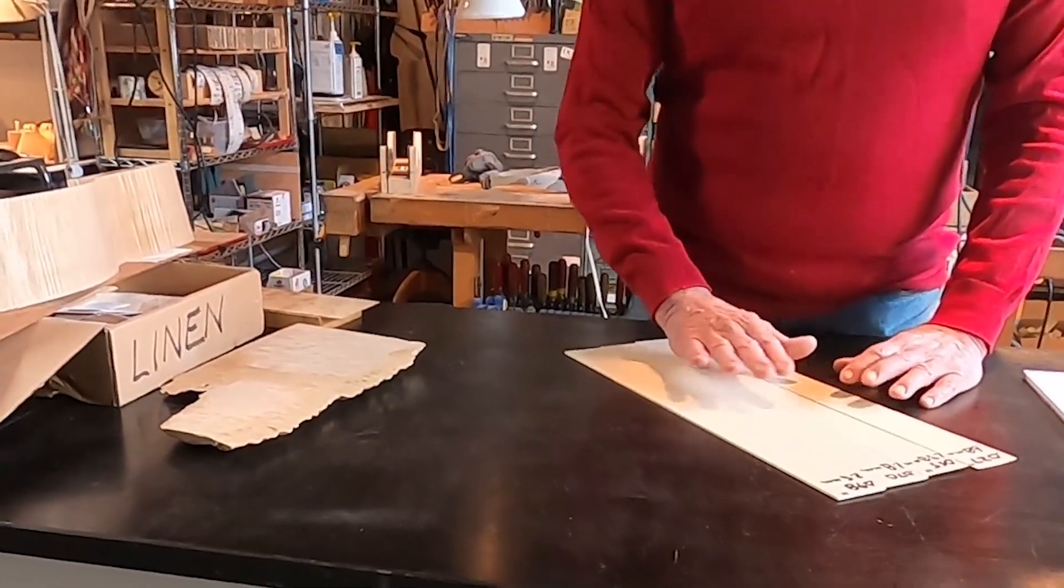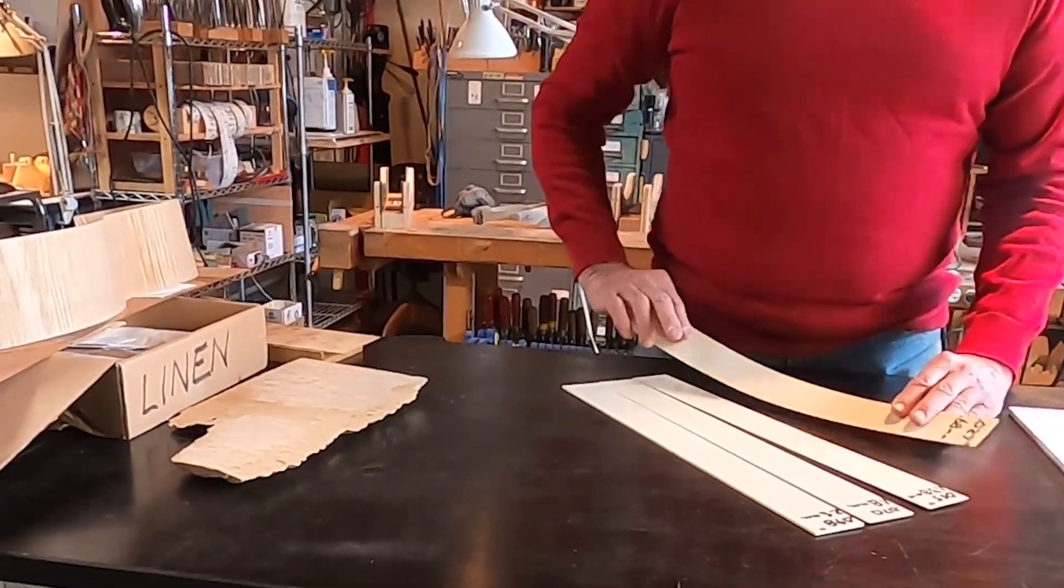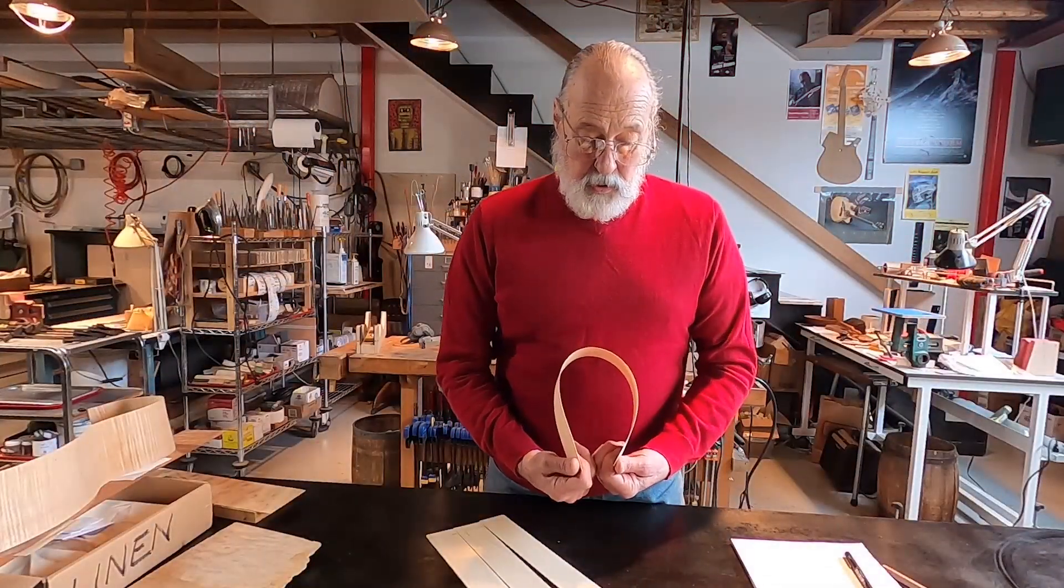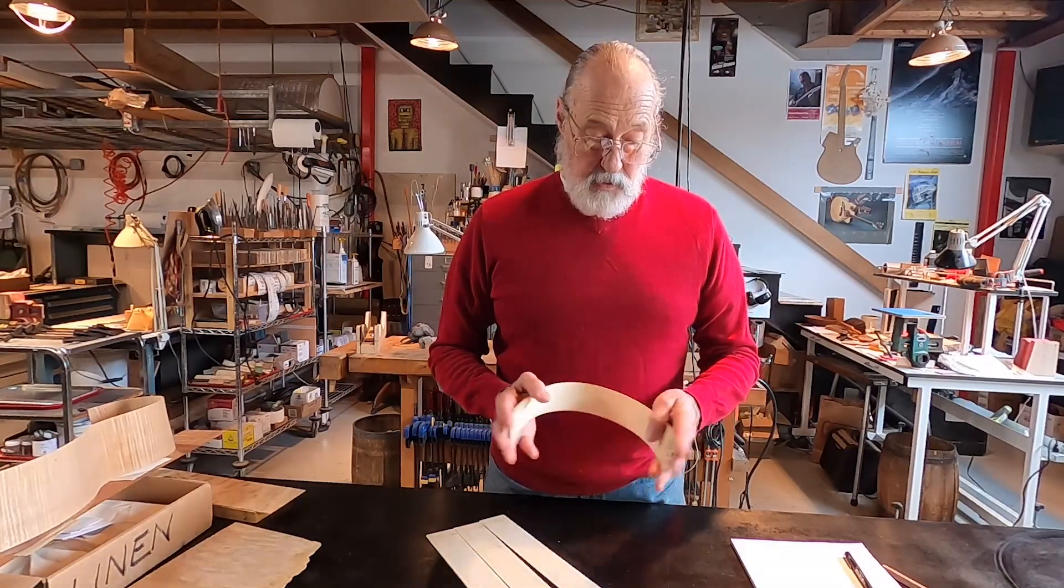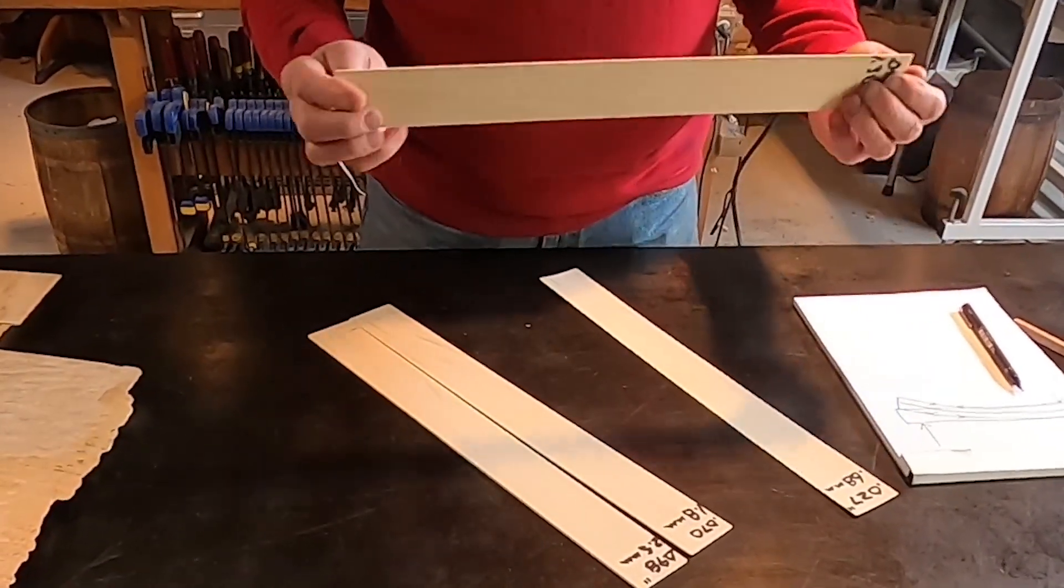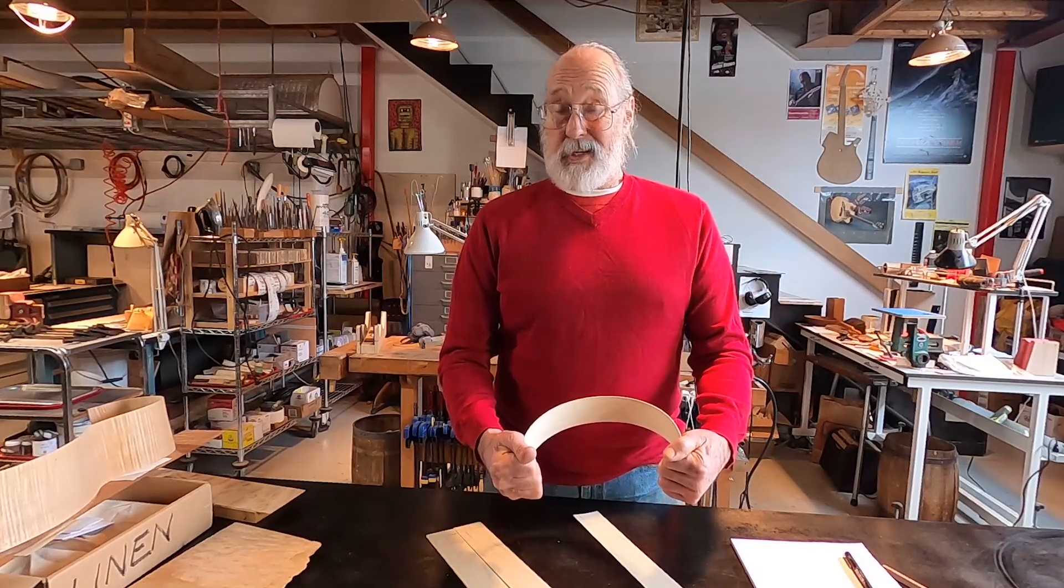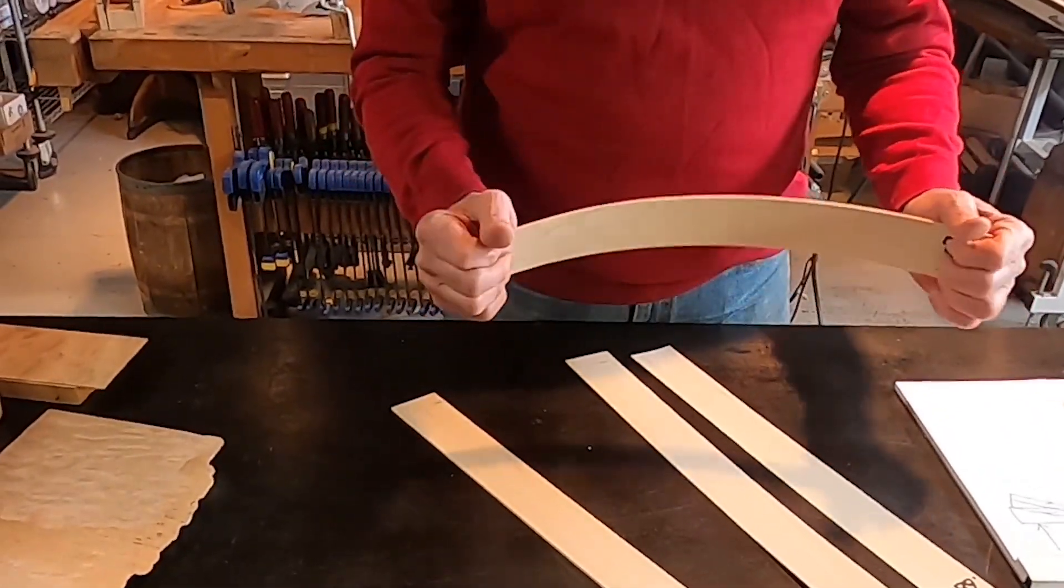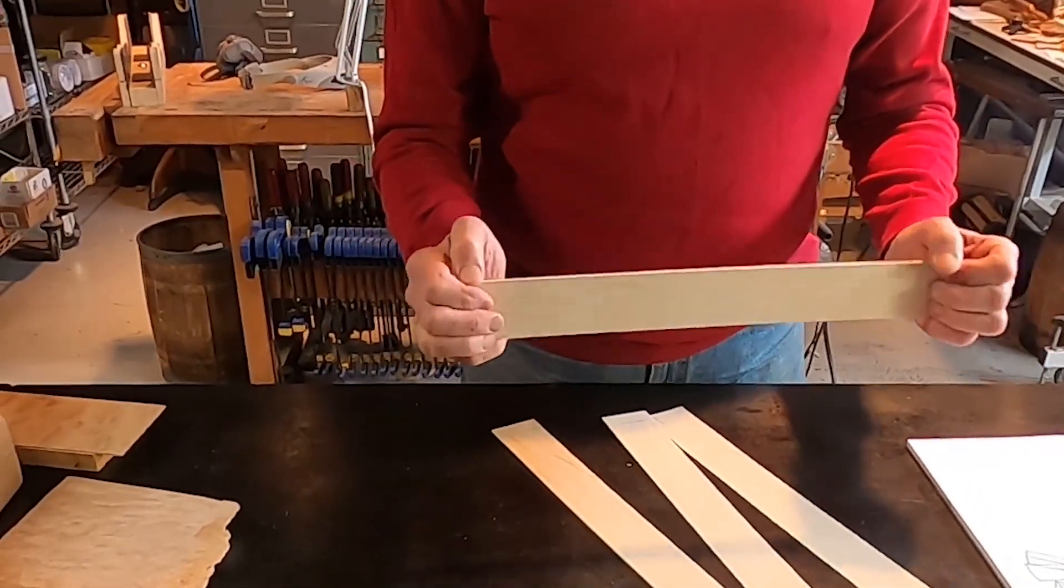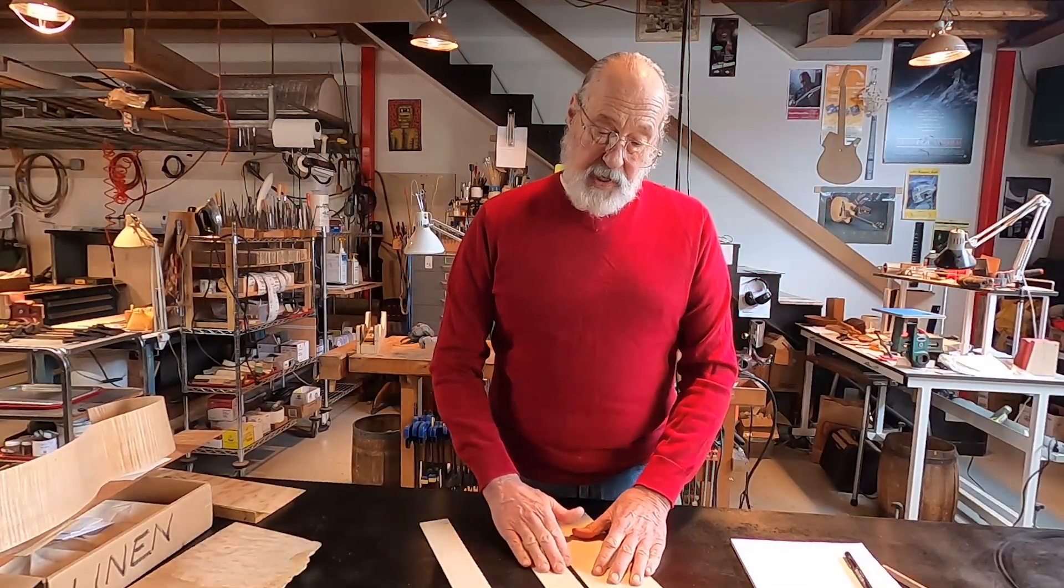So here I have four pieces of wood sawn from the same little board, and I've got four thicknesses marked here. This is 27 thousandths, or 0.68 millimeters. And of course, this is very bendy. Not a problem. We can make a circle out of this and it's not going to break. Now we have a piece 55 thousandths thick, and this is twice as thick. So when we try and make a circle out of this, I'm sensing this is about all I'm going to be able to get. I'm feeling like it's about to break here. If we go again, here's 70 thousandths, this one even less. And again, 98 thousandths, this is pretty stiff, really stiff.